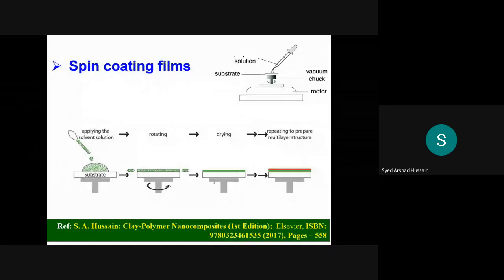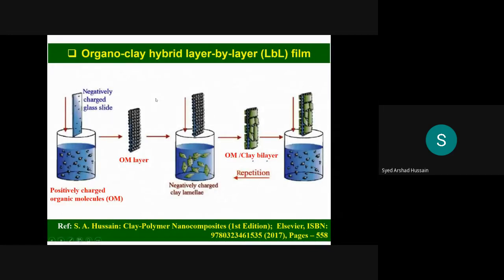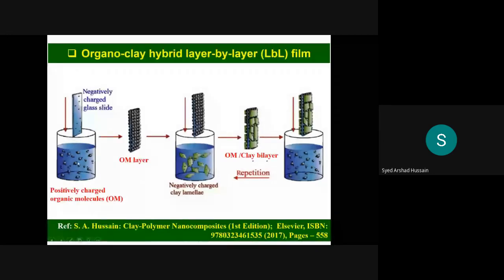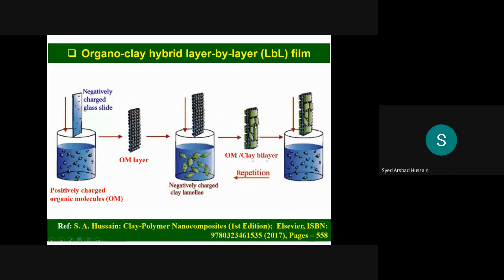This is again a layer-by-layer self-assembled system. What we do, we negatively charge the slides using some treatment, then we put them into the dye solutions and take them out. Through electrostatic interactions, the dye is adsorbed on the surface, then we wash and dry. Then we put the film in the clay dispersion, and through cation exchange reaction or electrostatic interactions, the clay attaches to these dyes, and again we take out, wash, and dry. So this is one layer of dye and clay, and by repeating the whole process, one can have the desired number of layers, the desired thickness, on the substrates.